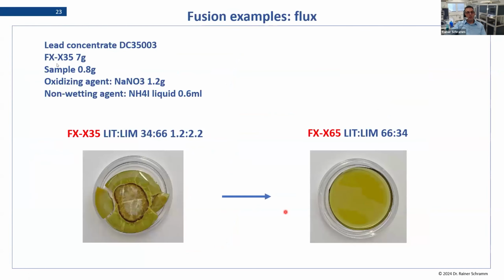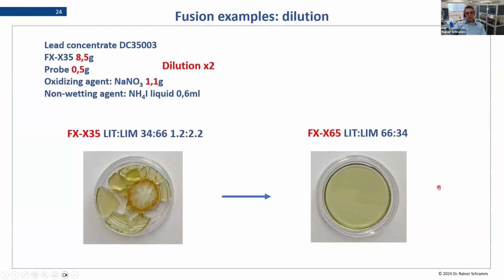Okay, some examples. For example, here I've used a lead concentrate, which was very difficult to fuse with this kind of flux. So you see here we have a partial crystallization, and it looks more like a ceramic. And if we change the flux, so we have more glass former, immediately you see that it becomes a bead. So here you see the difference using a flux with low tetraborate and high tetraborate, how this changes the glass forming behavior.